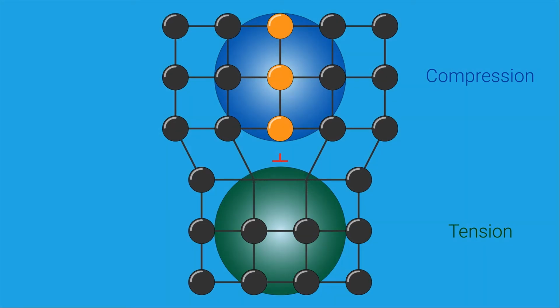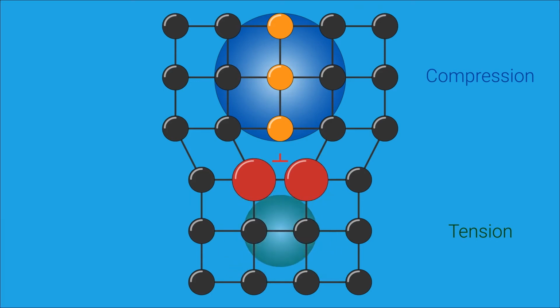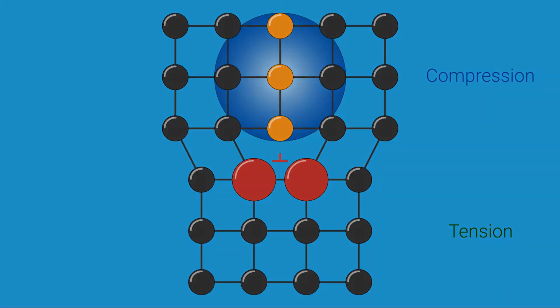The pushing compressive strain from molybdenum can interact with the pulling tensile strain from the edge dislocation, resulting in partial cancellation. This negation of strain fields is favorable because it lowers the overall energy of the lattice. The important consequence of this is that molybdenum atoms can lock edge dislocations in place, providing a barrier to deformation, and hence, strengthening the steel.